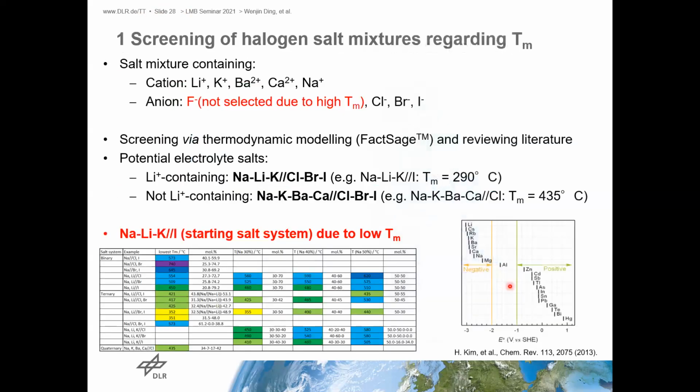Regarding the potential, the salt mixture should contain only the cations like lithium, potassium, and barium ions, because they should be more negative than the sodium metal, yeah? To have chemical compatibility with the sodium metal. And we also use the FactSage simulation, the thermodynamic modeling, to review this, and also review the literature.